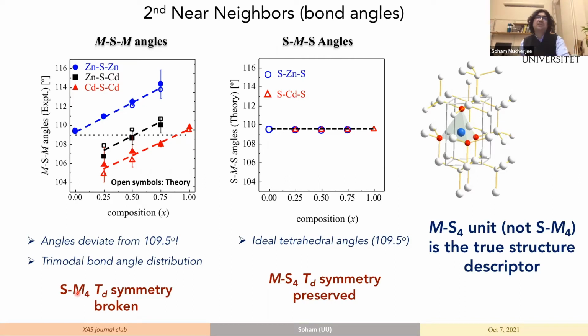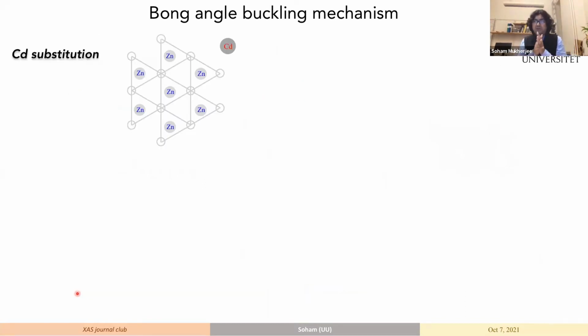So I tried to make a small cartoon to explain the distances, how the cationic sublattice is experiencing these kinds of effects. So you have tried to put in a cadmium at a zinc site. Cadmium is a larger ion, so it will immediately swell the tetrahedra. And we have seen that the cadmium sulfur distances are extremely rigid, very similar to cadmium sulfide, but this distance is now longer.